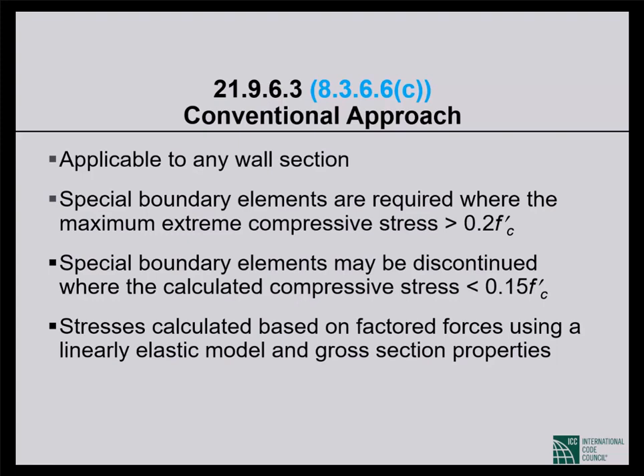So we go back to what we used to do. We calculate Pu divided by Ag plus Mu divided by Ig multiplied by 1/2 of Lw. If that sum exceeds 20% of f'c, then that triggers special confinement. The specially confined boundary zone may be discontinued where the calculated stress drops below 15% of f'c. 20% triggers it, but we cannot discontinue until we go below 15% of f'c. Stresses are calculated based on factored forces using a linearly elastic model and gross cross-sectional properties.